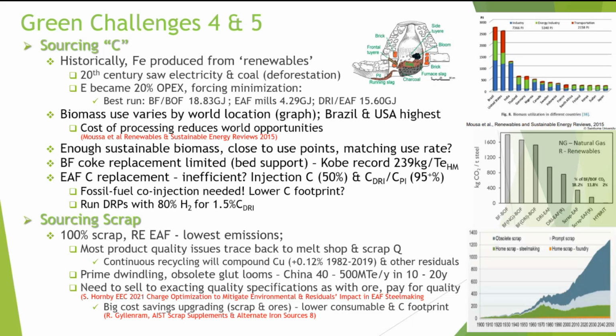The fifth sourcing challenge is scrap. For the 100% scrap EAFs, it's the lowest emissions, especially if you put renewable energy on. It drops it to about 0.18 tons of CO2 per ton.